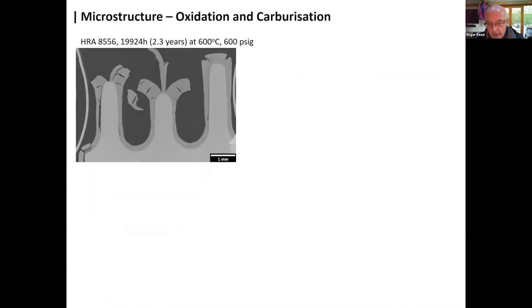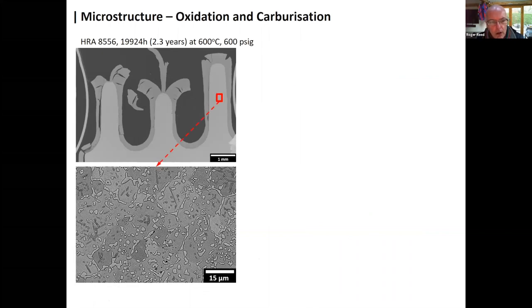So I'm going to start by just showing you some of the typical experimental work and observations that happen. So this shows you here now typical images of the fins. The fins are about 1 millimeter across here. And you can see there's quite extensive oxidation. These are accelerated tests after about 2 years. And you can see here that the fins have gone into so-called breakaway oxidation.